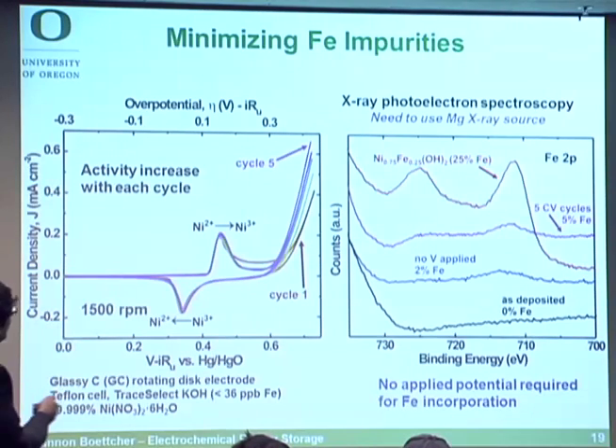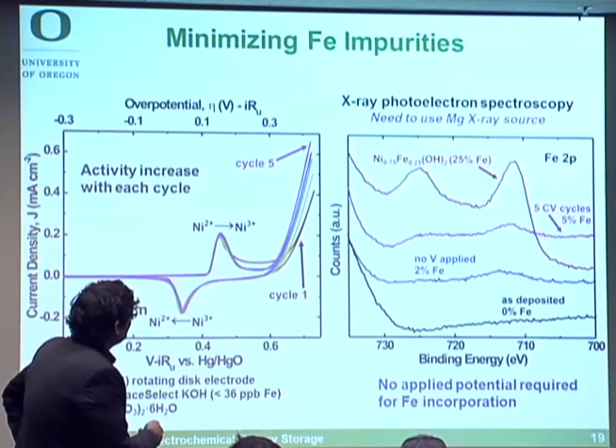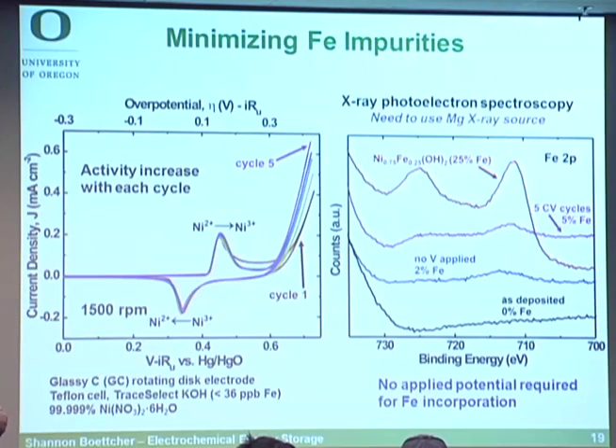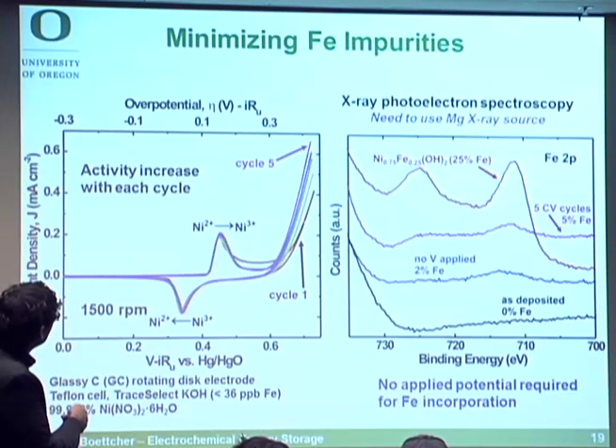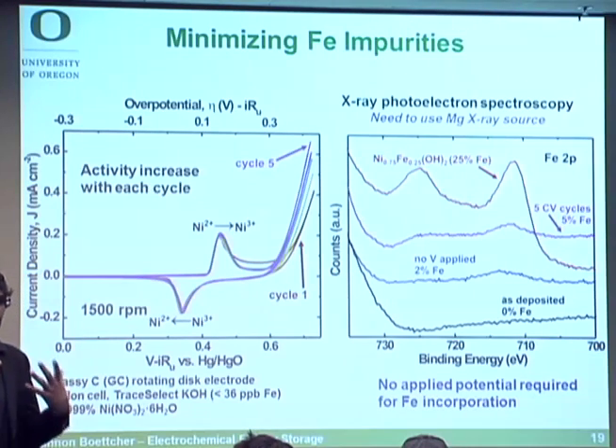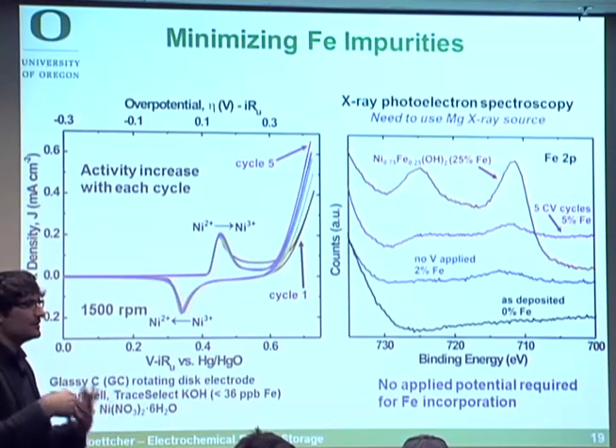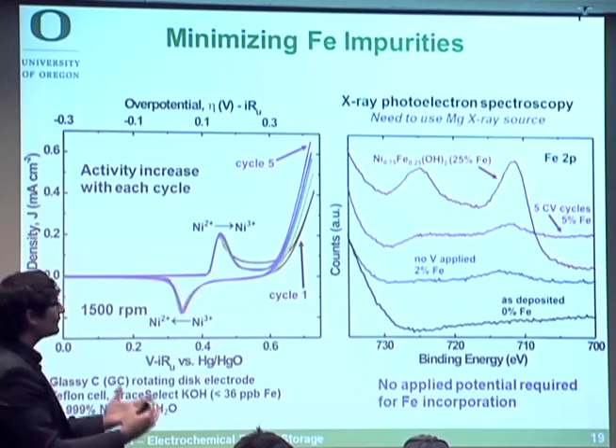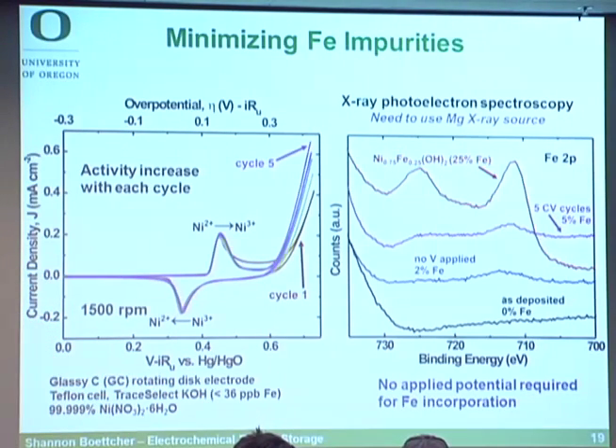And if you go and look in XPS, you can see iron if you use a magnesium source. And if you just deposit the film, you see no iron. If you put iron in intentionally, you see 2 large peaks. If you cycle it 5 times, this film, you see 5% iron at the surface. So it's amazing. 5% iron just by cycling this thing 5 times in this electrolyte. So it's sucking up every iron that hits the surface. It's going into this structure. Huge affinity for iron. If you do the same experiment but don't apply a potential, you get 2% iron after 10 minutes just sitting in the solution. Okay, so this is a problem.